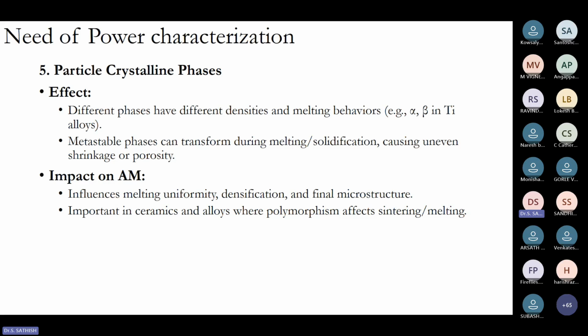So these differences in phases lead to different densities and melting behavior that will affect the properties of the additively sintered components. The change in transformation of phases will lead to a shrinkage of material or the formation of porosity during additive manufacturing. Thus, it will impact the melting. There won't be uniform melting of the material during this change in phases, which affects densification. So there will be shrinkage during this change in behavior, and that will result in porosity formation. In turn, it will affect the metallurgical behavior.